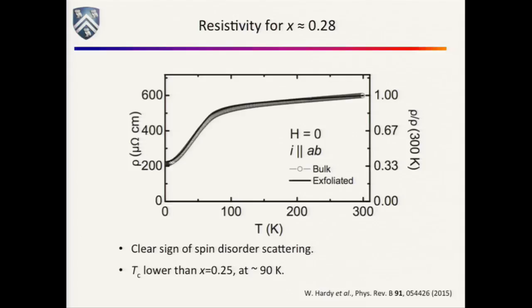Here's the comparison of resistance versus temperature for the bulk and the exfoliated thing, and they really lie on top of each other, right? Again, the TC, and this is x of about 0.28. Notice that only going from a quarter to 0.28, TC has fallen quite a bit, right? If I take the derivative of this curve, I can really see where the transition is. It's around 90 Kelvin. So you've hurt the stability, if you will, of the ferromagnetic state. But it still seems to have all the anisotropy and everything.